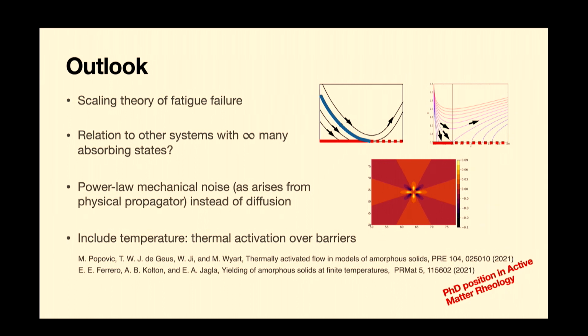because the way stress propagates from a plastic event is actually in a power law fashion. So you get some very large stress perturbations, some very small ones, and the mechanical noise is not Gaussian as supposed in the Hébraud-Lequeux model, but has a power law distribution. So there are interesting connections there also to Levy walks and Levy dynamics. And then there's a further question, which is what happens if you start including thermal activation over barriers? So far everything we've done is athermal, so what happens to the phenomena I've described once you start adding small amounts of temperature is also an interesting question.